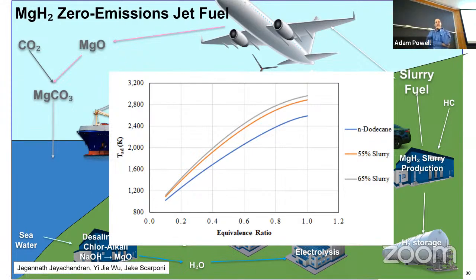We did some thermodynamic calculations, which were just accepted by the journal Fuels. This will be our first journal publication on this, showing that for a given equivalence ratio, with 1 being stoichiometry, and 0.5 meaning that you have twice the air that you need, half the fuel, you get to a considerably higher temperature with magnesium hydride. And that means that if you have a certain target temperature based on what temperature your turbine can handle, you can burn leaner using less fuel, more air. I mentioned that Jake Scarponi is here. He did some of the work on this, both the combustion tests, and also some of the research on atmospheric interactions, and Yi Jie Wu as well.